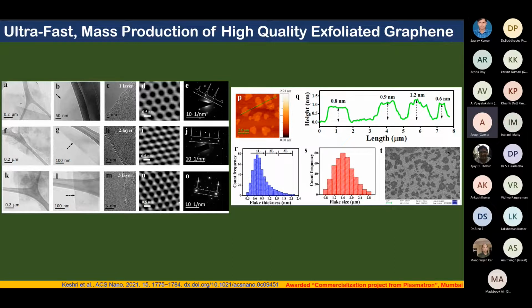Now similarly F, G and H. If you compare images C, H and M just below, you can find the layers visible. This is a single layer, then the two layer, where you can see two lines on the edges, and at the bottom you can see three layers, right? When you place the two layers, the top hexagon changes into a rectangular one, and when you place the three layers, it becomes triangular.